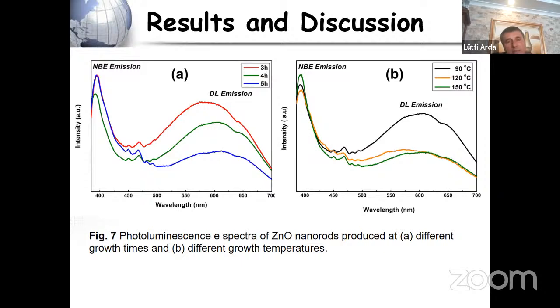Also, we can measure band gap using the PL measurement result, but the correct one is using the Tauc plot. Near band emission originated from the excitonic transition between electrons and holes in the conduction band and the valence band, respectively. The stronger ultraviolet emission is observed in zinc oxide with higher crystallization quality and fewer defects. This is important for the crystallization quality of the samples.